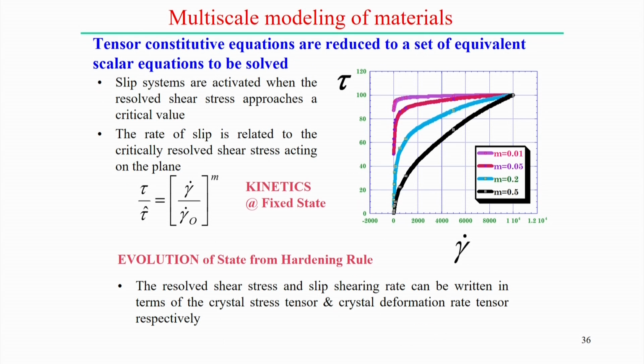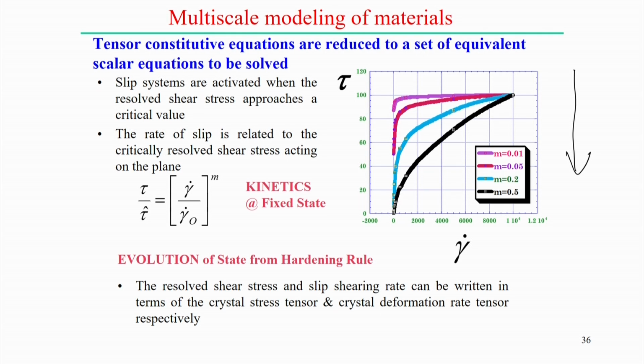Now the tensor constitutive equations are reduced to a set of equivalent scalar quantities. We have already explained that sometimes we represent the stress tensor in an equivalent form, a single scalar quantity. Slip systems are activated when the resolved shear stress approaches the critical value. That is true, but the rate of slip is related to the critically resolved shear stress acting on the plane. That is the relation between the shear stress and the rate of shear strain. Accordingly, we can consider the kinetics as a fixed state. In the figure on the right-hand side, for different values of m, this constitutive relation between stress and strain rate can vary.